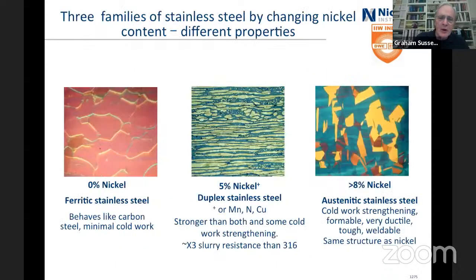But if you don't add quite enough, then instead of going from the ferritic stage straight to an austenitic stage, you wind up in the middle with a duplex. In a duplex, instead of adding 8% nickel, you've added about 5% nickel or other variants of it. Or you can add manganese, nitrogen, copper, and so on. And you get this alloy, which is stronger than both the ferritic and the austenitic, and behaves a bit like the austenitic in terms of cold work strengthening. And interestingly, if you're looking at slurry resistance, then it's about 3 times better than 316, but we'll get to that sort of thing.